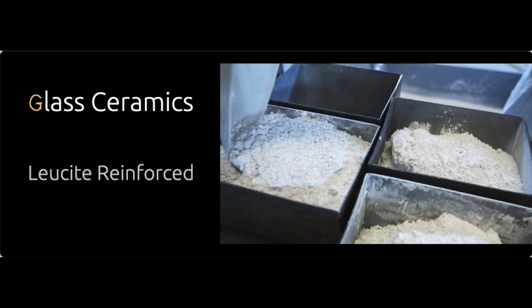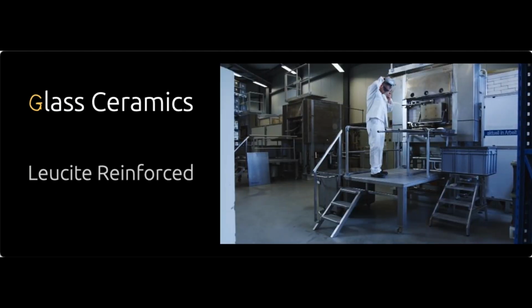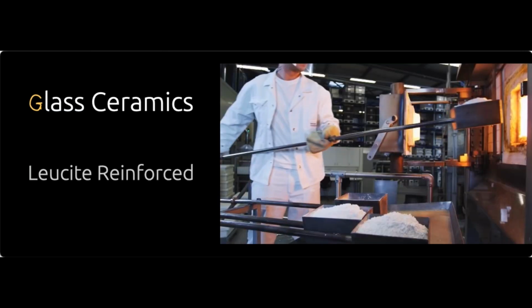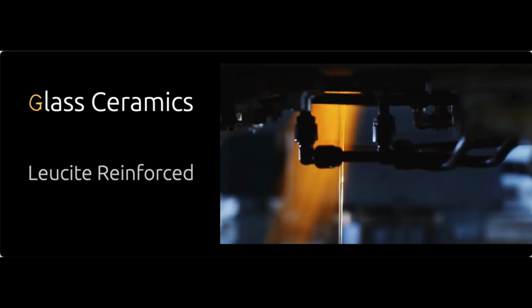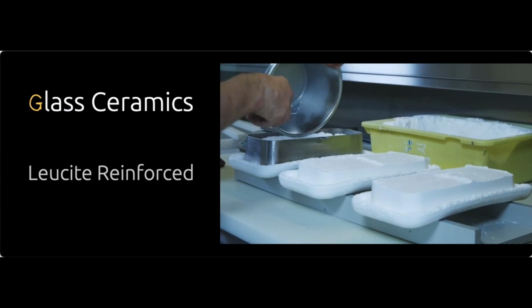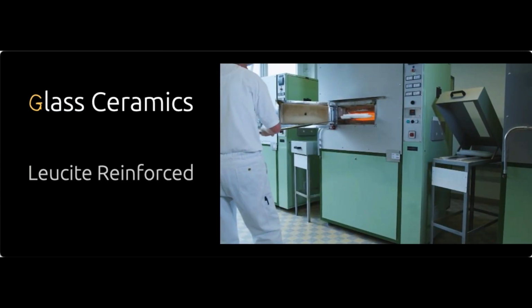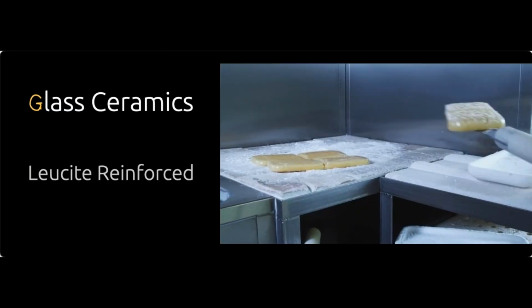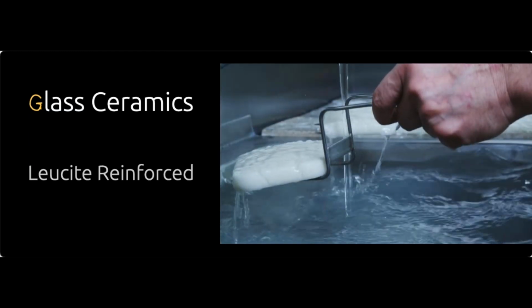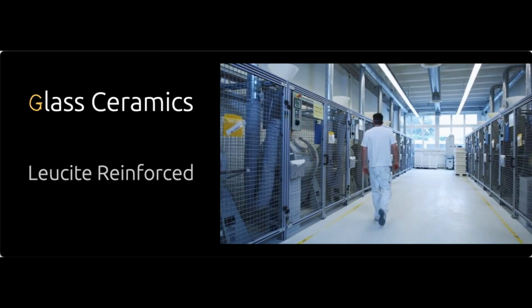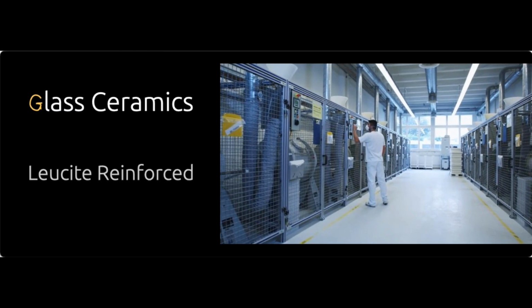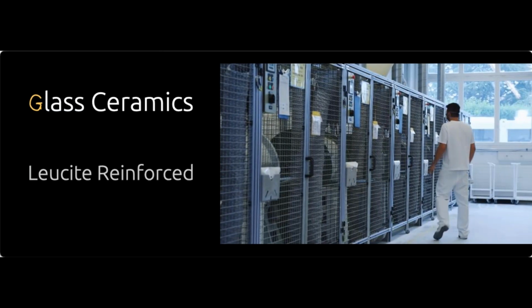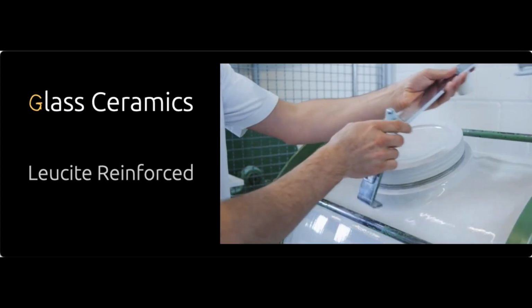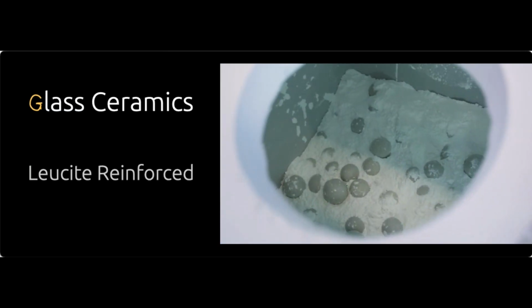You see, they get glass from the real world and they make it into a powder, and then they're going to get that powder and put it into the oven and cook it as a piece of glass. And as it comes out of the oven, they're going to quench it into water, and then when they quench it into water, then they're going to mill it again into another powder, and they're going to do things here. The manufacturing process for glass ceramic is different in every company.